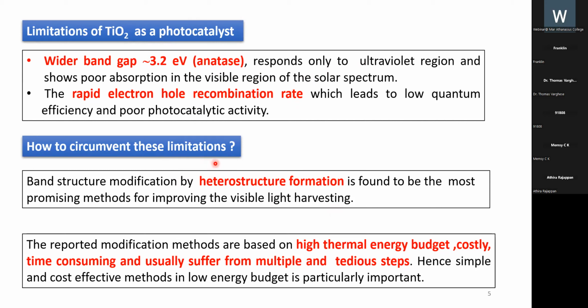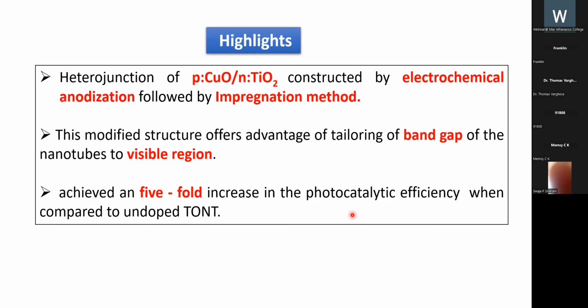Intense efforts have been made to shift its optical response to the visible range. Band structure modification by heterostructure formation is found to be the most promising method for improving visible light harvesting. But the modification methods found in literature are based on high thermal energy budget, costly, time-consuming, and usually suffer from multiple and tedious steps. Hence, simple and cost-effective methods with a low energy budget are particularly important. Highlights of this work are heterojunction construction of PCuO and TiO2 constructed by electrochemical anodization followed by the impregnation method. This modified structure offers the advantage of tailoring the bandgap of the nanotube to the visible region, achieving a 5-fold increase in the photocatalytic efficiency when compared to undoped TONT.